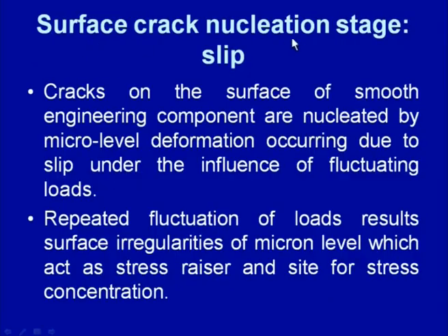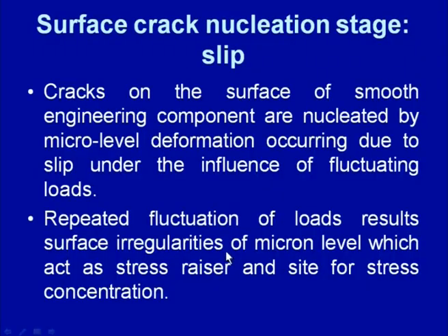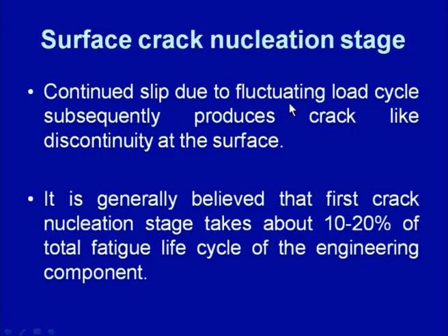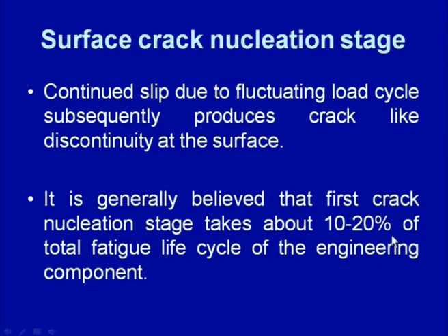So as far as the surface nucleation stage by the slip, we know that the cracks on the surface of a smooth engineering component are nucleated by the micro level deformation occurring due to the slip under the influence of the external loads, and repeated fluctuation of loads results in surface irregularities at the micro level, which act as a stress raiser and the site for the stress concentration. Continued slip under the fluctuating load cycle subsequently produces crack like discontinuities at the surface, and it is believed that the first crack nucleation stage takes about 10% to 20% of the total fatigue life cycles of the engineering component.